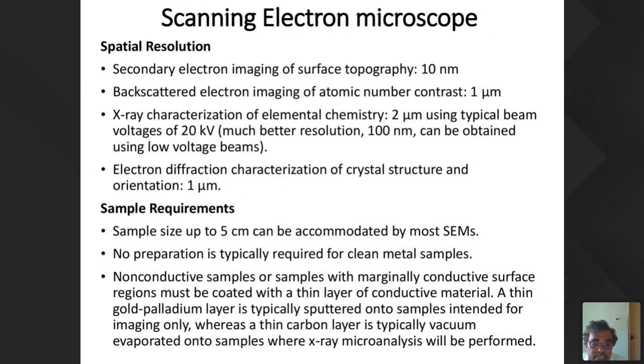The resolution for secondary electron imaging of surface topography is 10 nanometers. With backscattered electrons in SEM it is 1 micron, X-ray characterization of chemistry is 2 microns, and electron diffraction characterization of structure is 1 micron.